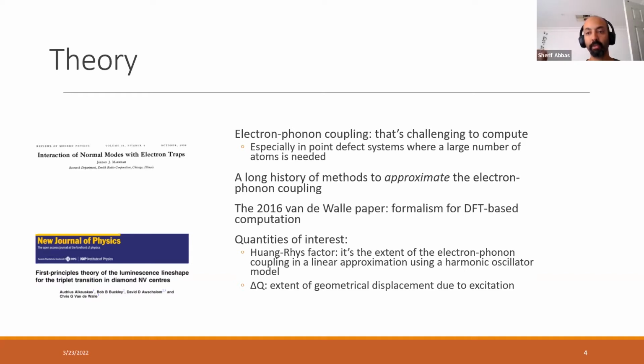They compared the prediction of the photoluminescence line shape for a particularly interesting defect in diamond, which is a nitrogen-vacancy defect in diamond, which is a negatively charged defect. And they expressed the mathematical equations there. They used VASP at the PBE level, and also at the HSE level. And obviously HSE, not really obviously, but it might be expected that HSE was the most accurate in predicting the photoluminescence line shape. And also the Huang-Rhys factor.